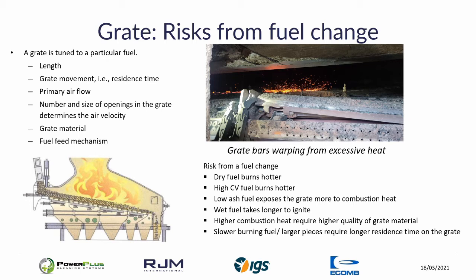So if you suddenly introduce a new fuel, these are the sort of things that you have to consider. So very often you end up potentially with a drier fuel. Many of the original grates were designed for coal, and they're now being asked to burn biofuels, wood pellets, and obviously these are much drier. And then you have this concern that you have to deal with the much hotter fuel on the grate. And this image here, which you may be able to see, shows a damaged, warped grate bar because it's overheated. So these things have to be considered.